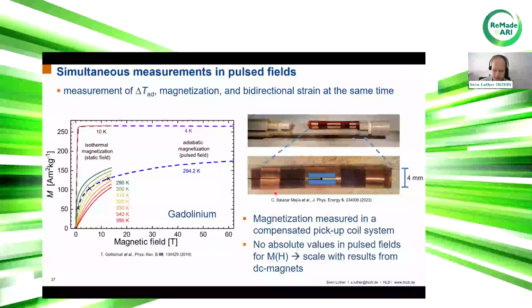And in the end, at these ends here, we have the compensation of the coil, so they compensate the background to only get the magnetization from our sample. And here you can see the magnetization of the gadolinium. These small curves up to 14 Tesla are measured in static fields, and these dashed curves are the measurements in pulse fields.